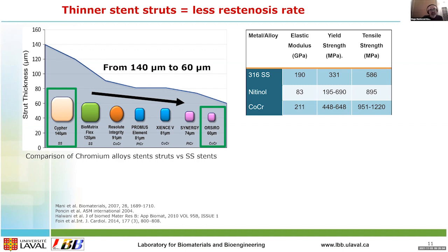For 60 micron, the stent is extremely thin, so one of the main problems is the radiopacity. So how do you implant this? Let's have a very quick look at the mechanical properties: stainless steel, chromium cobalt, and nitinol. I would say this is my personal statistic, so I cannot cite it, but 60 to 70% of the stents worldwide are made of chromium cobalt. Stainless steel was at this number 10 years ago.